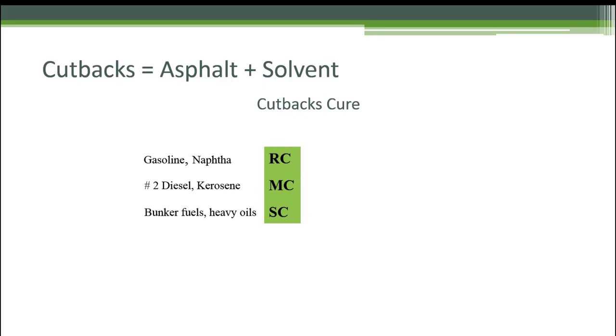And then the last one is SC, slow cure, and the solvent in that is a bunker fuel or a fuel oil. And that was used primarily for winter mixes. If I needed to put some mix up in a pile that I had to have over the winter, because if I have a water line break and I gotta dig everything out, but I gotta repave it, and I can't use gravel because it's frozen, and I want something hard surface, so I'm not out there every morning after freezing, I'd have a pile of SC mix, and I could go in, and after I kind of got through the surface, the skin, I had mix underneath.